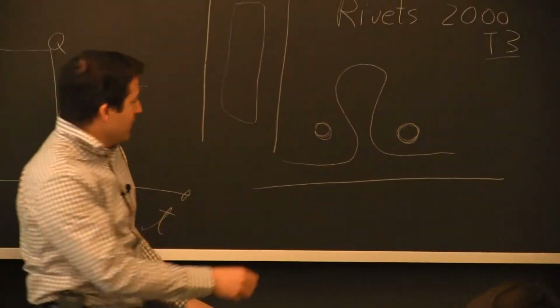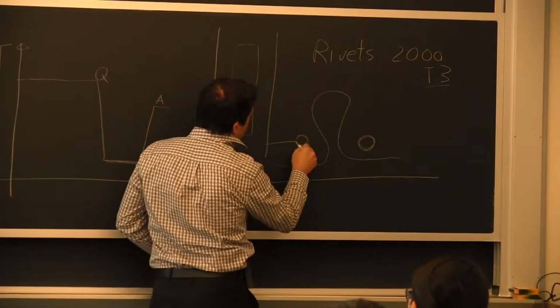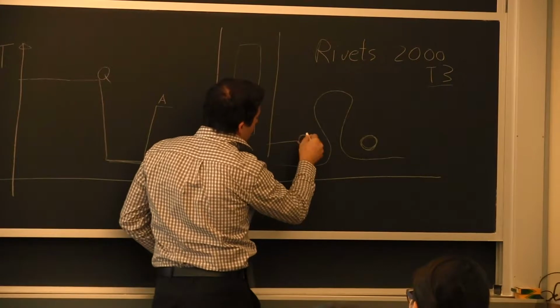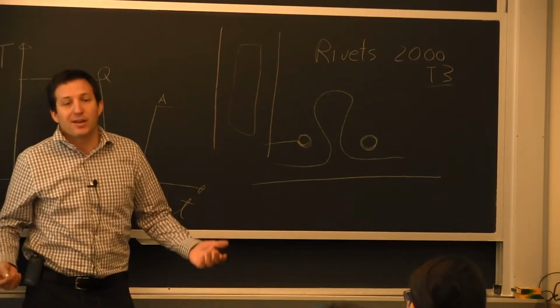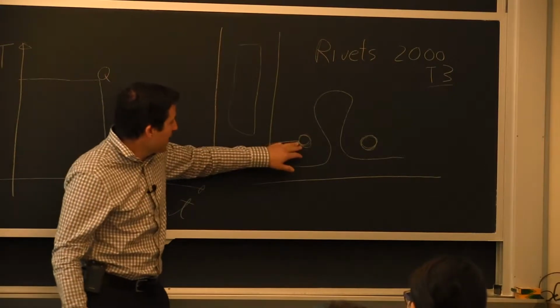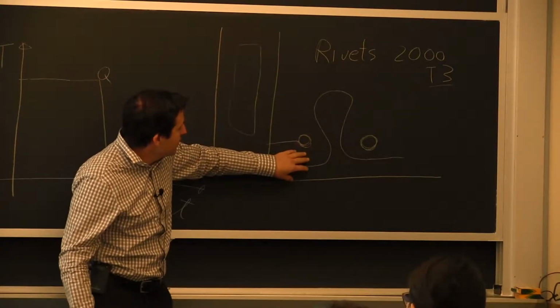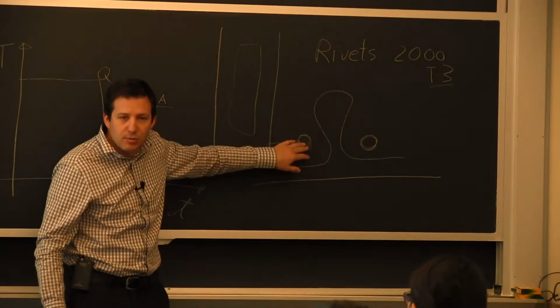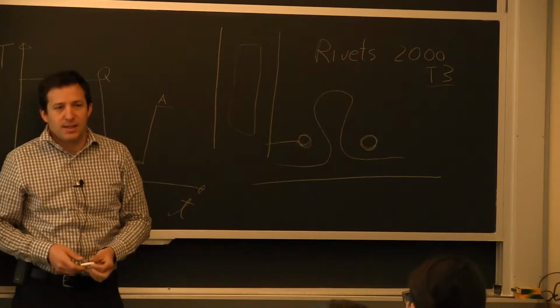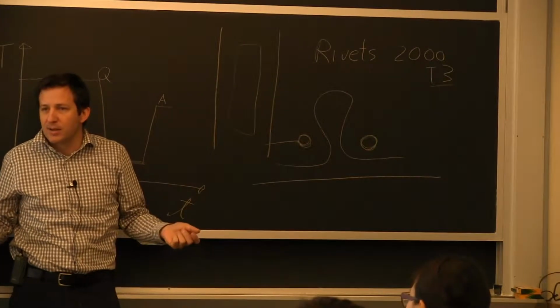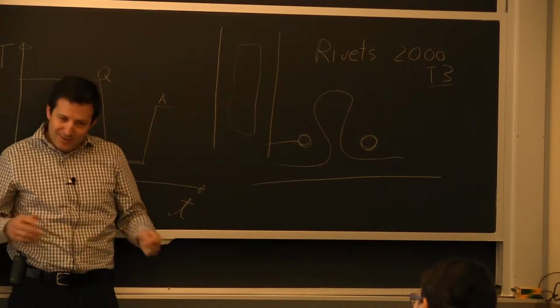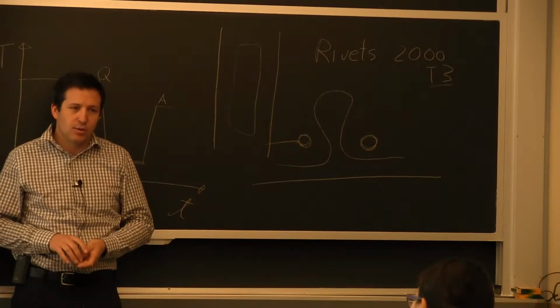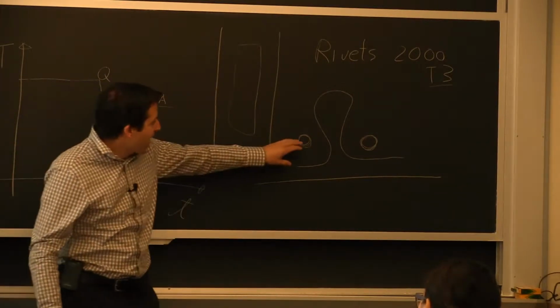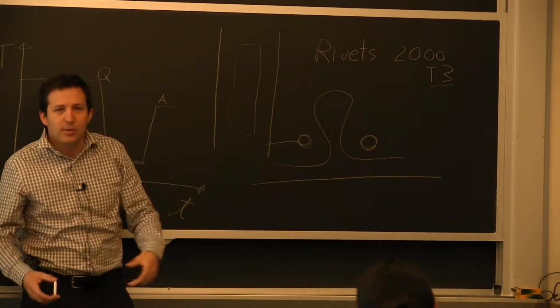When you see it's going down, it's because now these precipitates are becoming so big that the dislocation will just come around, and if you don't have a coherent interface, it will just jump around it. Right on that interface, it's a little bit like a grain boundary at that point. It doesn't feel that there's a precipitate until it reaches it, and then it just goes over. So at that point, the precipitate is just too big. So too small, too big, they don't do a whole lot. It's in between, and that's why you go through a peak here. And the exact shape of the precipitate will vary over time.